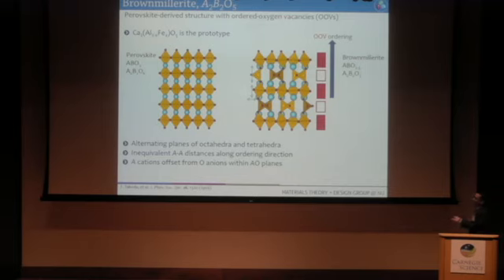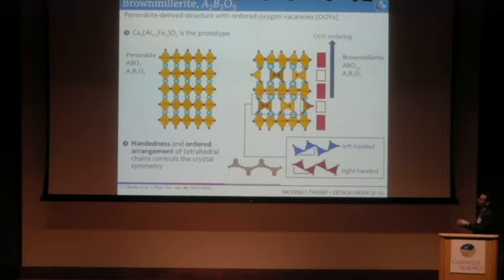Okay? The thing I want to focus on then is this tetrahedral chain. So it's a chain structure into the board. So if I pull out this chain structure of the tetrahedra, I can define an idealized chain where the chain has, say, 180-degree linkages in this direction going into the board. In all of the equilibrium structures, these chains can tilt with a left-handed or right-handed sense. It doesn't really matter which one you define. There's just two types of them. I've colored one blue and one red. And these two-handed tetrahedral chains, when they're rotated, do have dipoles along the chain direction. Okay? So this local unit, this chain, has a dipole associated with it. And in brownmillerite, the manner in which these chains order determines whether or not the structure has inversion symmetry. That's the key effect. And these symmetries are protected by the glide operations in the space group.